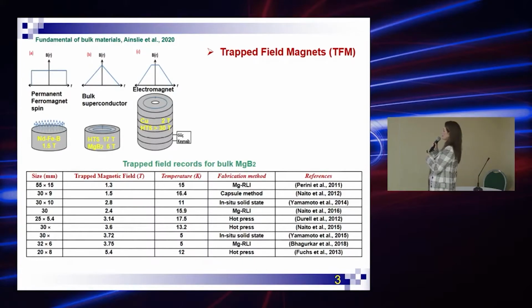So I want to gather the trapped field records for bulk MgB2. While rare earth barium cuprates can have high JC and so high trapped field values, such as today's record of 17.6 Tesla at 20 Kelvin in gadolinium barium cuprate, it is difficult to make large, high quality single grain samples over 60 millimeters in diameter.